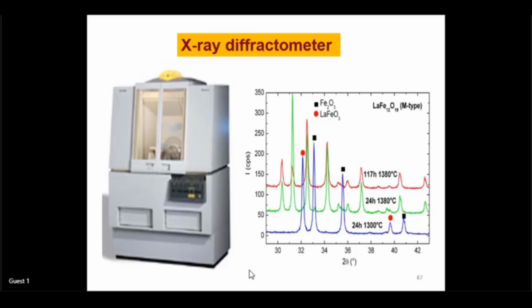and on the right hand side, the chart that is known as an X-ray diffractogram. Here this is an M-type material, but it is not barium or strontium, it is lanthanum based. And I was mentioning, to check the phase purity, and crystallite size also can be checked. Not only that, but you can decide the lattice parameters, for example a, b, and c, and cell volume, and so on. So if you see the red dot marks in some of the charts, it shows that LaFeO3 is formed. Then if you see the square, it shows that Fe2O3 is there. So these samples are not pure. They have two secondary phases, Fe2O3 and LaFeO3.